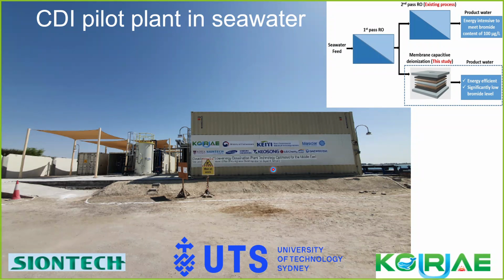We have collaborated with a Korean project to demonstrate seawater desalination after first-pass RO, and we connected the second pass RO. This is the general RO process, and we tried to replace the RO second pass with MCDI, and saved almost 0.3 kilowatt hour per cubic meter, so a huge amount of energy can be saved from this process. We demonstrated this 1,000 cubic meter per day energy efficient desalination in the Arab Emirates, and successfully installed this process and demonstrated it.